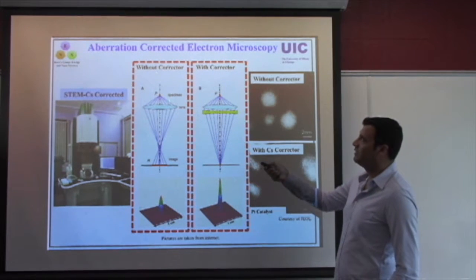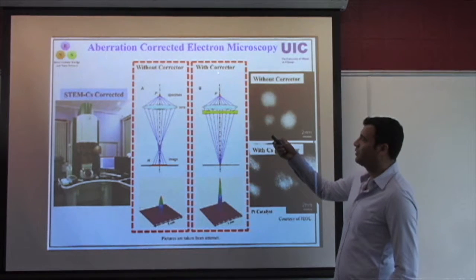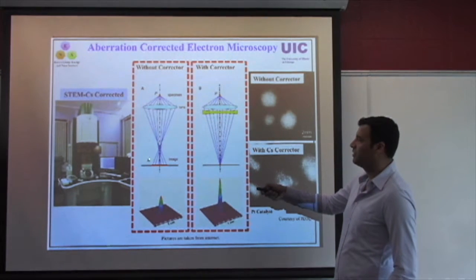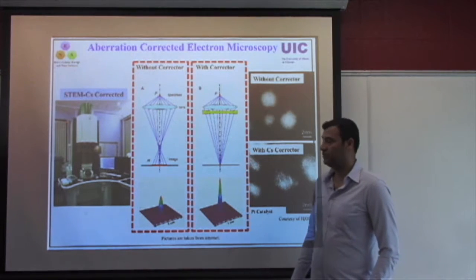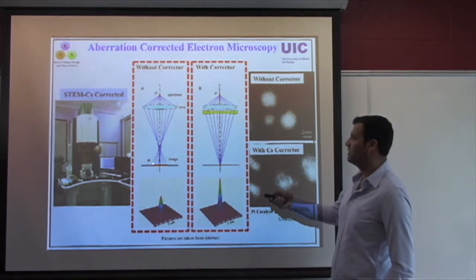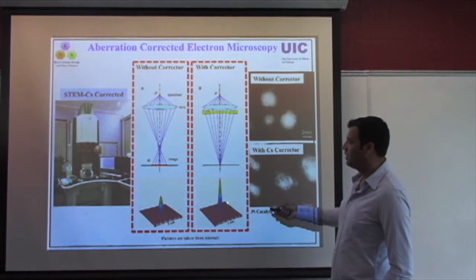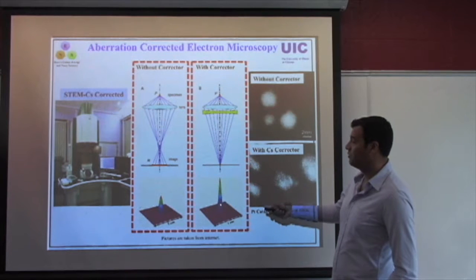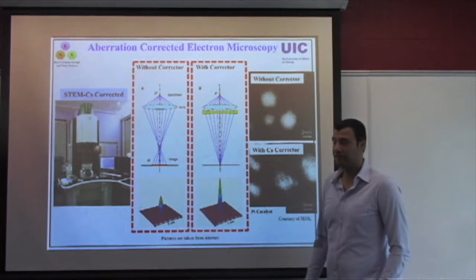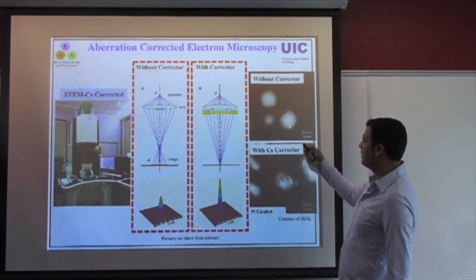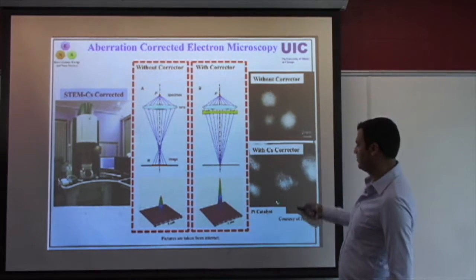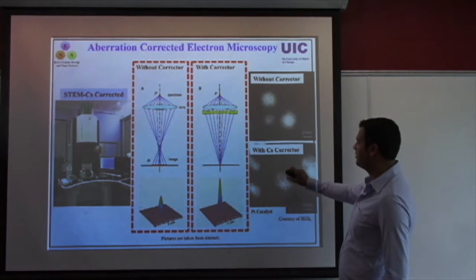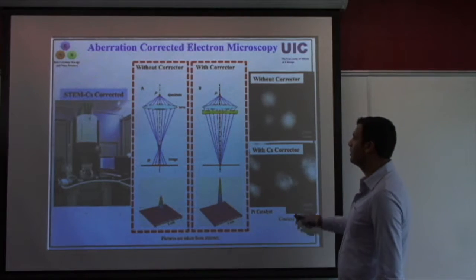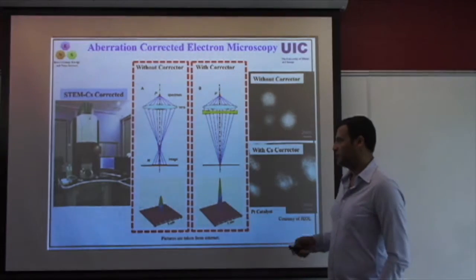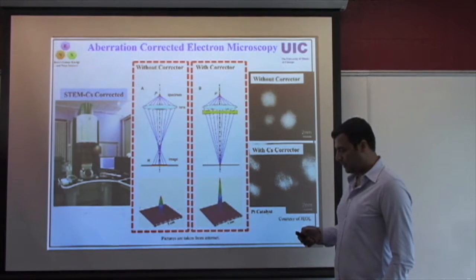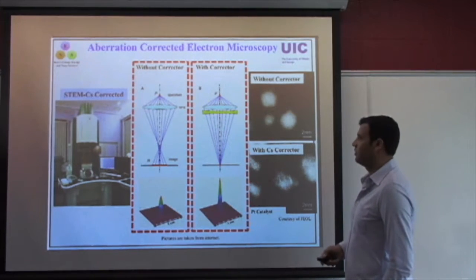If you compare a non-corrected microscope versus a corrected microscope, as I already discussed, you have a disk of uncertainty in the image, a fuzzy image, and the probe is not quite sharp compared to the case when all the beams converge at a point. So you get far better current density at the point, which helps you get far better image resolution. This is an example of platinum catalyst systems, where you can now observe atomic positions and atomic columns, while here you see a fuzzy image, making it difficult to know about the atomic order in this particular catalyst.